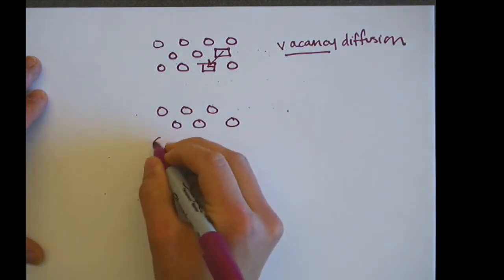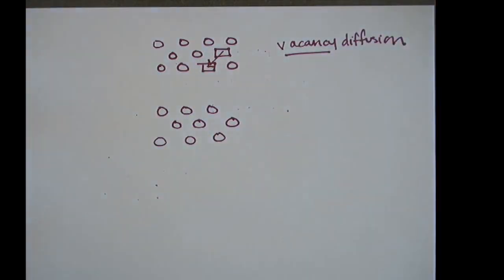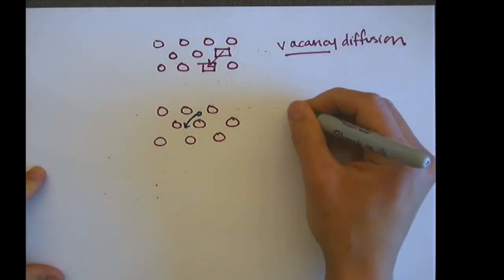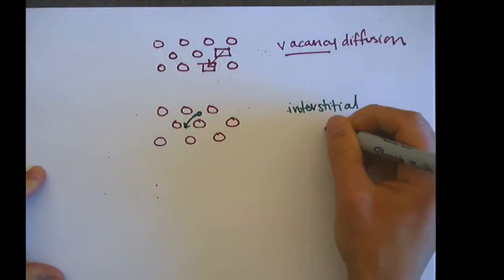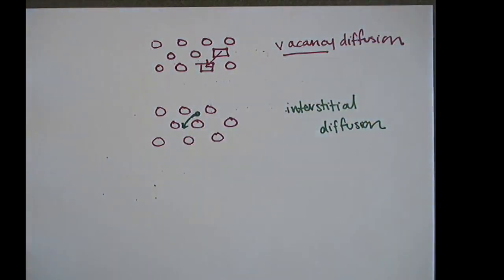Now the requirement is that there has to be a vacant site next to it that is open. Next, we're going to show interstitial diffusion, so I'm going to draw the same lattice, but now remember our interstitials are really small, and those move from interstitial site to interstitial site. This is interstitial diffusion. So the reason that interstitial diffusion happens so much more quickly than vacancy diffusion is that the lattice strains induced by this little interstitial impurity is a lot smaller than the lattice strains induced by the vacancy diffusion. Those molecules are a lot bigger, so to get from site to site, it'll incur a lot more lattice strain, which has to do with the activation energy, which we're going to talk about next.